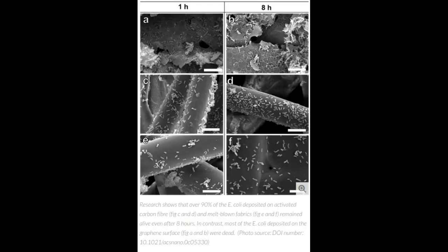the antibacterial efficiency of activated carbon fiber and melt-blown fabrics, both commonly used materials in masks, were only 2% and 9% respectively.